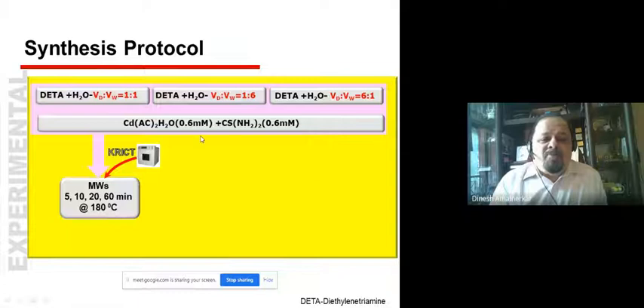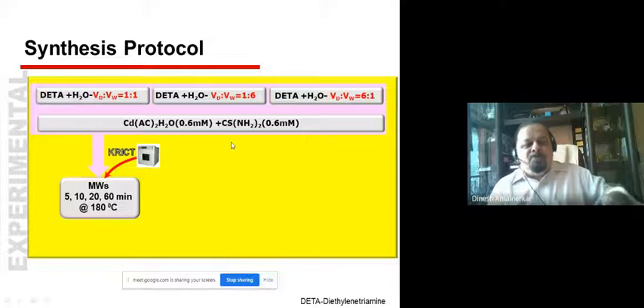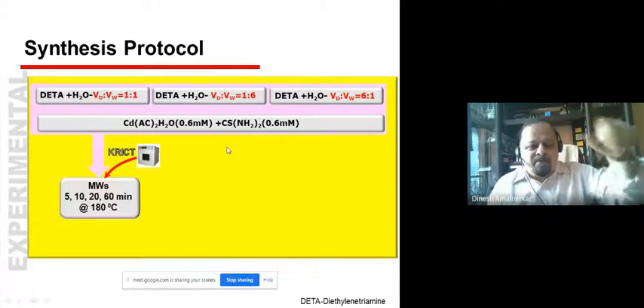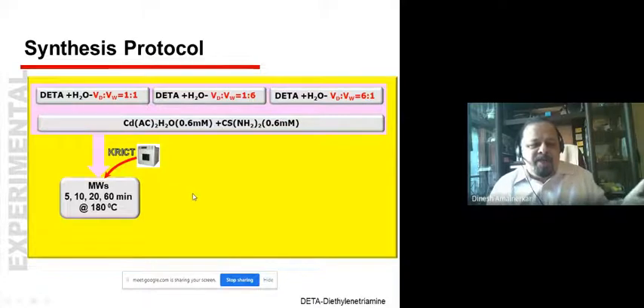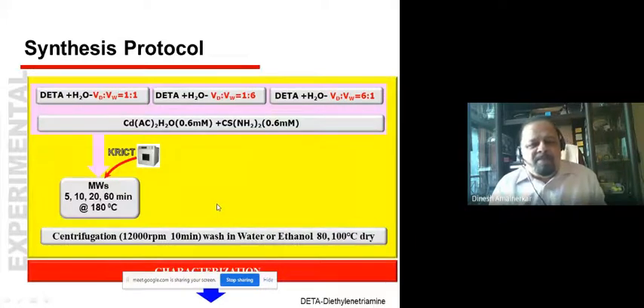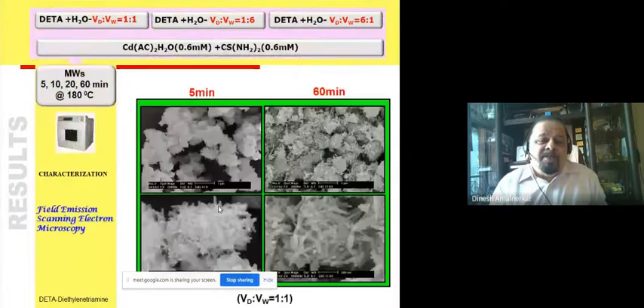So instead of conventional heating mode, like the Chinese researchers, 180 degrees centigrade, 12 hours, we switched over to this particular microwave, which was available in Korea Research Institute of Chemical Technology. We did heating for, say, 5 minutes, 10 minutes, 20 minutes, 60 minutes, and we could get exactly the same results which the Chinese researchers had obtained at 180 degrees centigrade for 12 hours of heating. So let us see. This is one particular volume ratio. We can see this FESEM, maybe these are old FESEM images taken at Korea Research Institute of Chemical Technology.